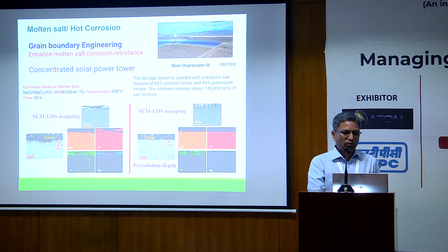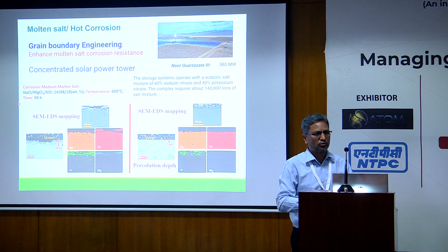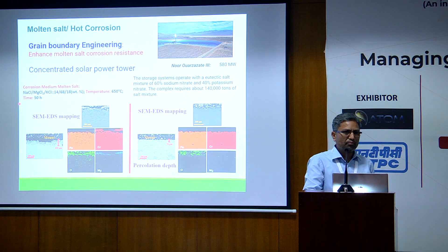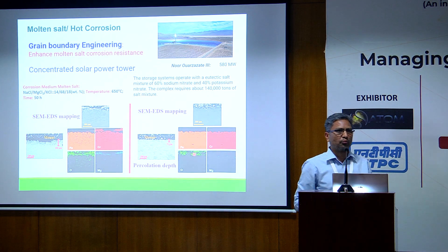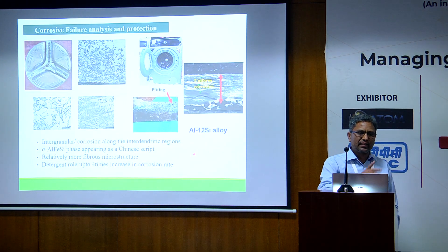Chloride salt — such as magnesium chloride, sodium chloride, or potassium chloride — has high heat capacity. But the issue is corrosion: the material hosting this much salt will be affected by corrosion, and chloride salt makes the material susceptible to pitting corrosion. At high temperature, oxidation is also a concern. We tried grain boundary engineering and showed it can reduce percolation of localized corrosion along grain boundaries. The grain boundary engineered material has about 70% low energy boundaries along with disruption of high random high-angle boundaries, and we can reduce corrosion by about 50%.